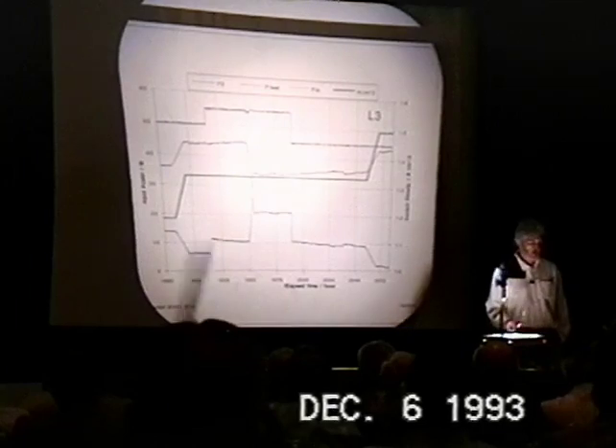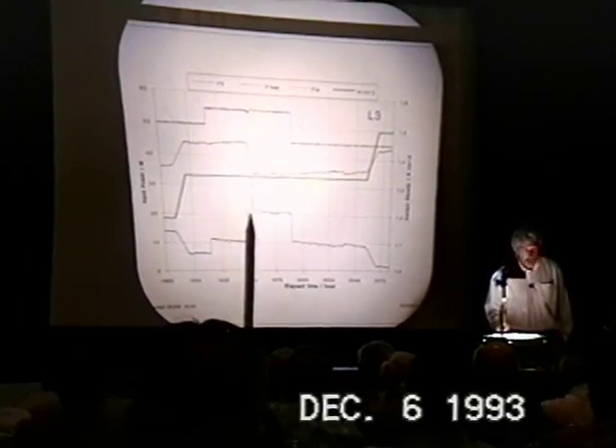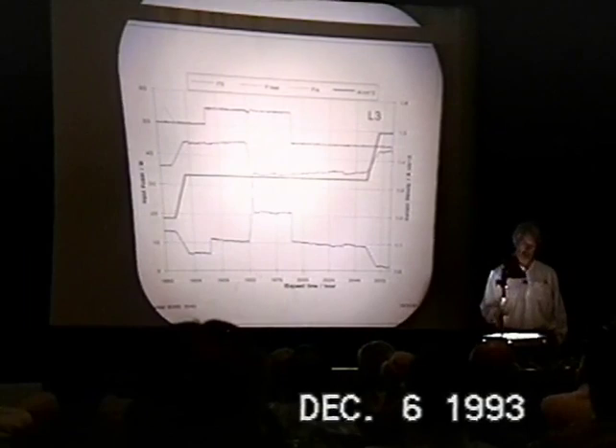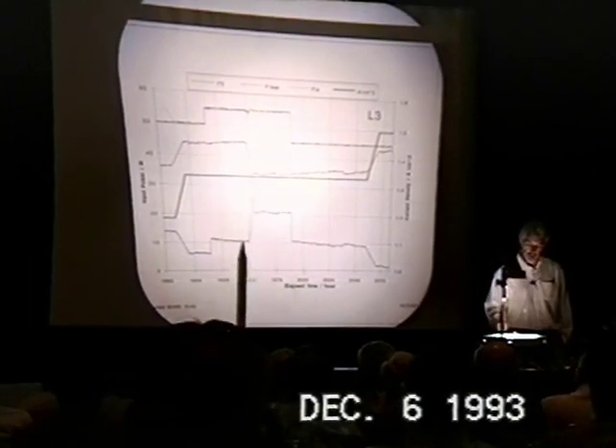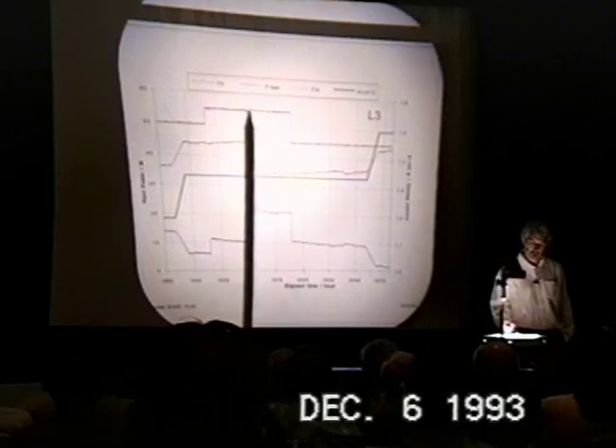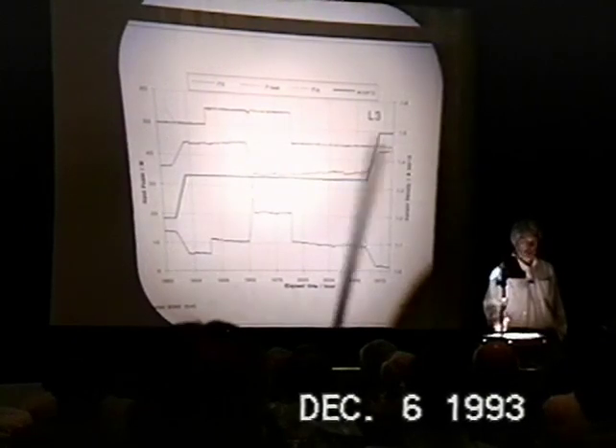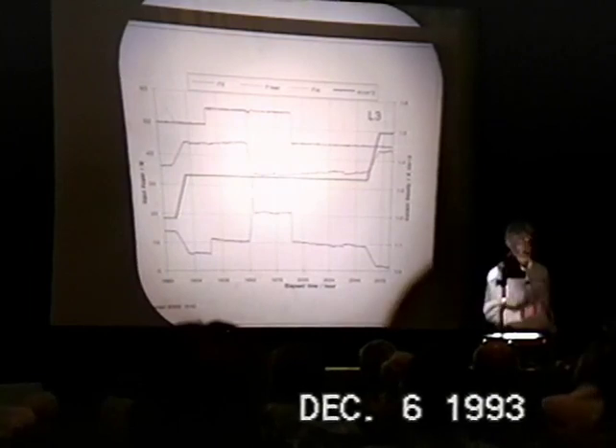What happened was the temperature went up, the electrochemical power came down because the resistance of the electrolyte decreased. The heater compensated almost perfectly. You can see a little wiggle here, so that the constancy of power was maintained, but the electrolyte got very hot.